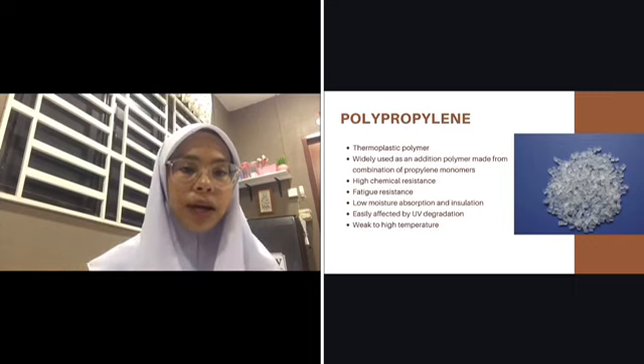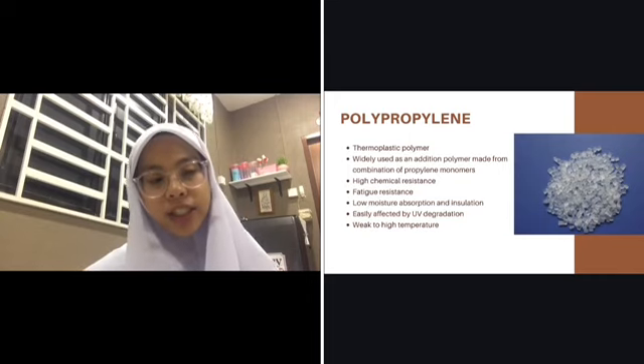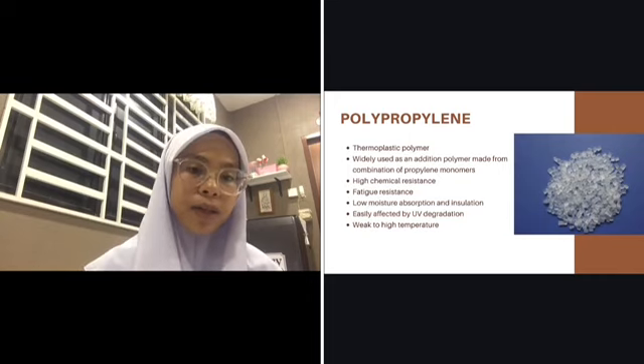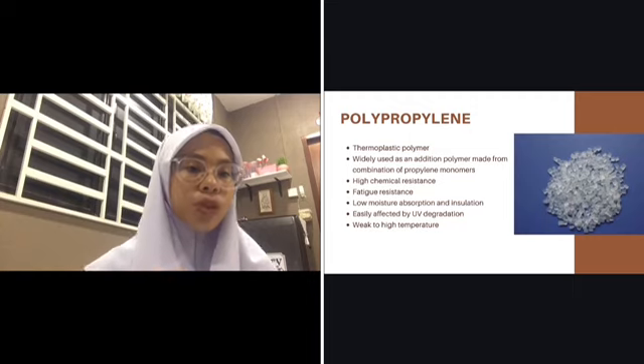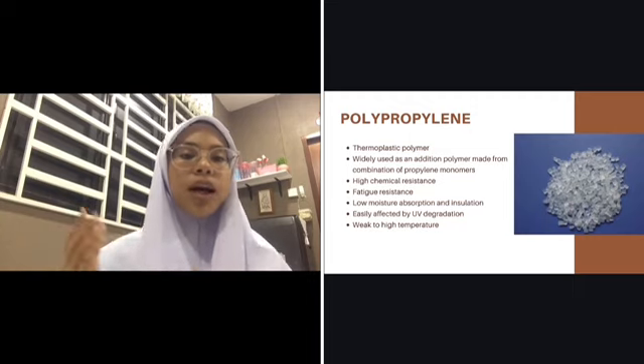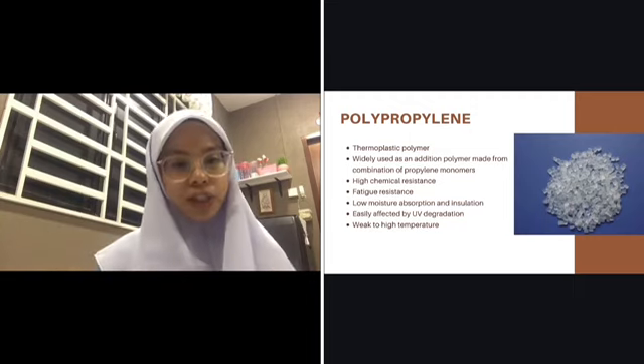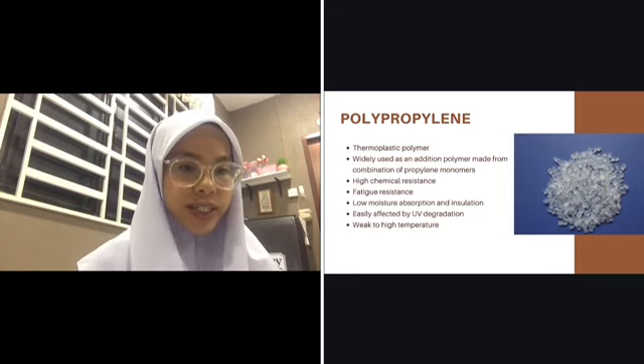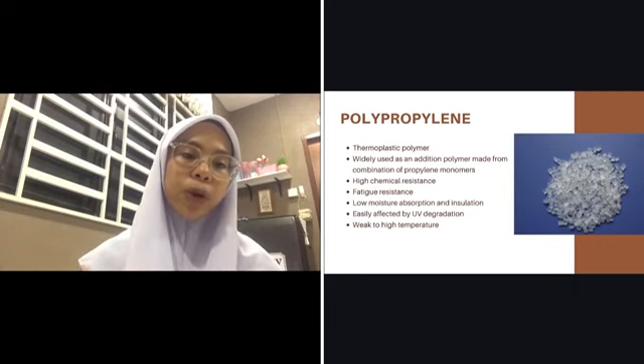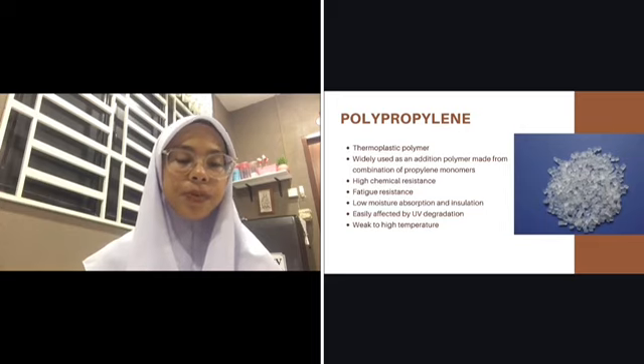However, polypropylene is easily affected by UV degradation, thus it is unsuitable for use in high places or altitudes where the UV penetration is high. PP is also weak to high temperature, where its performance values decrease after reaching 82.2 degrees Celsius.